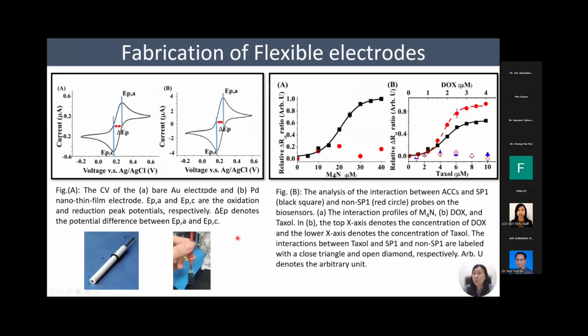So then we try to study the CV curve, that is, the stability of this palladium nano thin film. You can see that the study shows that the palladium nano thin film exhibits a peak potential difference of 74 millivolt, which is similar to the standard gold electrode as shown here. So this study suggests that the developed palladium nano thin film exhibits electrochemical properties that are comparable to those of a gold electrode.